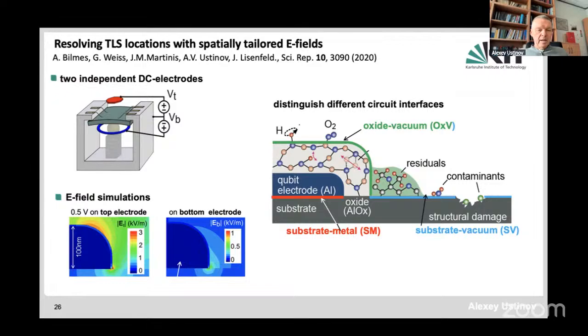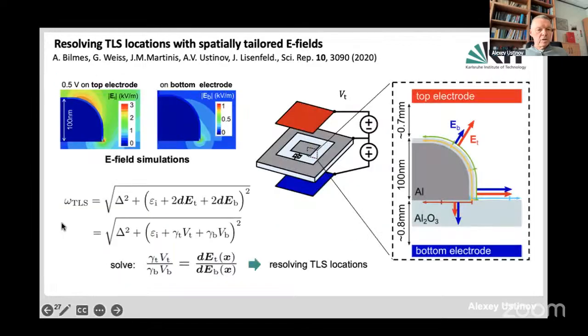And then by comparing the distribution of the electric fields as a function of coordinate, in the system of coordinates we have chosen here, the origin was here at the corner of the superconducting film. And then we go either in direction left or along the curved surface on the right, on top, or go to the right along the substrate. Basically, we have one-to-one correspondence of the ratio of the amplitude change induced by the vertical field produced by the top electrode, and the field produced by the bottom electrode.